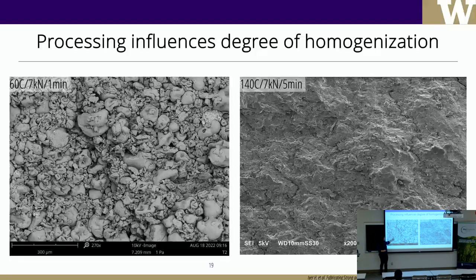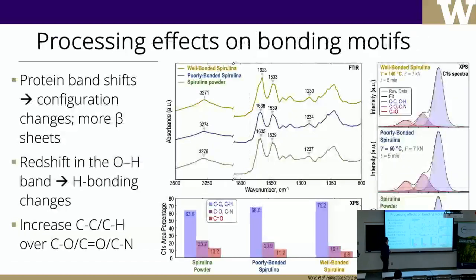In this case, you just have loosely packed powder. You can distinguish all the cells, and you can see this comes from a large chain, this comes from a very tiny chain, or even maybe a single cell. And you can see that even though it was strong enough to be measured, so we're not talking about powder, you still can actually grab this with your hands, but this is very poorly bonded compared to this, where it's basically an amorphous blend of everything connected. This is just from the morphological point of view, of course.